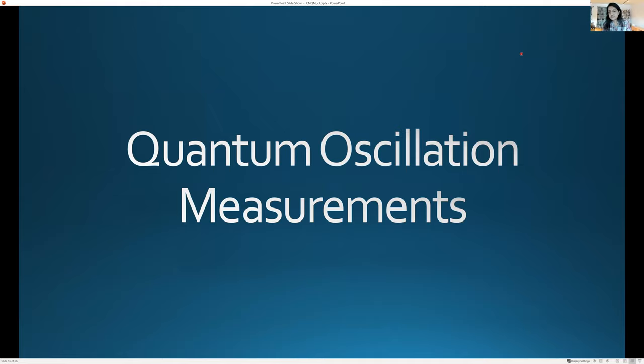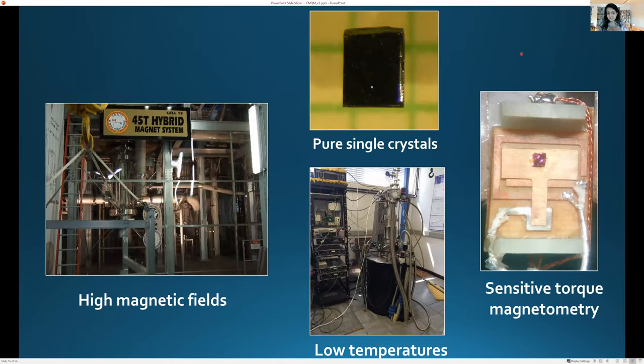We then start trying to look for quantum oscillations, as I mentioned, motivated by the fact that we were trying to see what the Fermi surface of the conducting surface of a possible topological insulator would be. So we go to Tallahassee, use high magnetic fields up to 45 tesla. These screened single crystals at low temperatures down to dilution fridge temperatures, and using torque magnetometry. So just to give you a very, very brief outline of torque magnetometry.